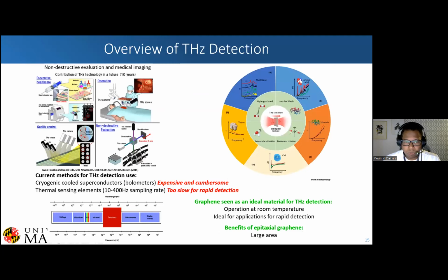And so one of the things is, okay, well, why are we interested in THz detection? Well, really, not very many materials, like I said, interact with it. And so typically you have cryogenically cooled superconductors or bolometers. These are expensive and cumbersome simply because you have to have some mechanism of cooling them down. Thermal sensing elements are cheaper, but the sampling rate is at most 400 hertz, and they generally are much lower, going down to 10 hertz. And so they're really too slow for rapid detection.